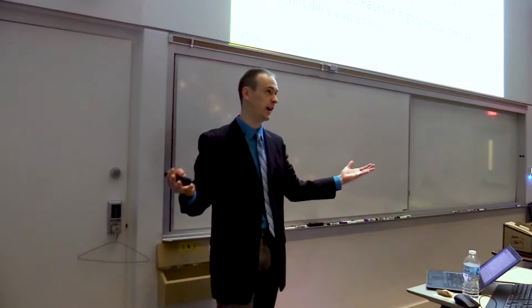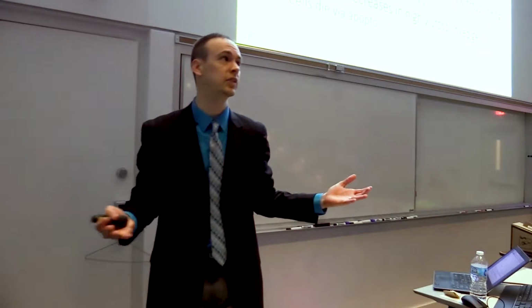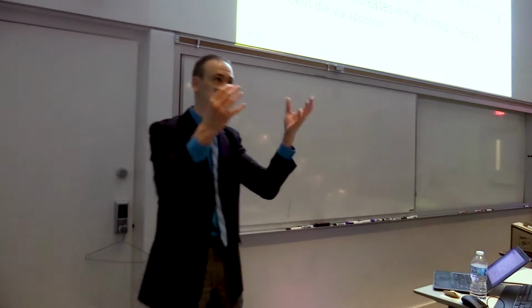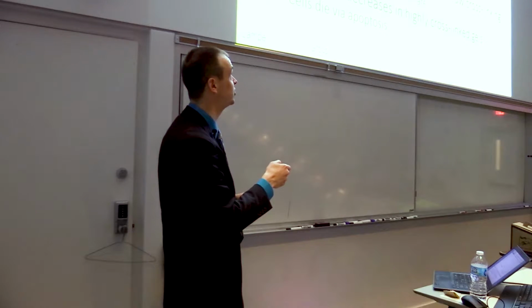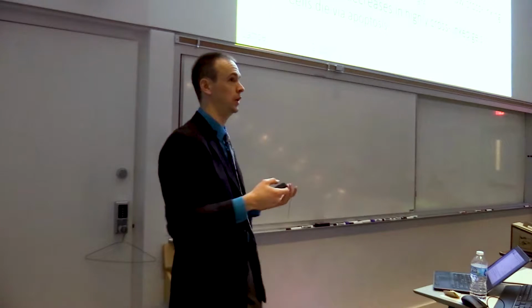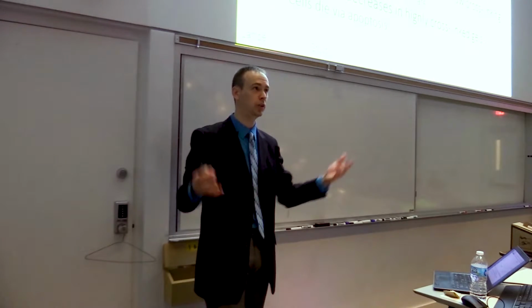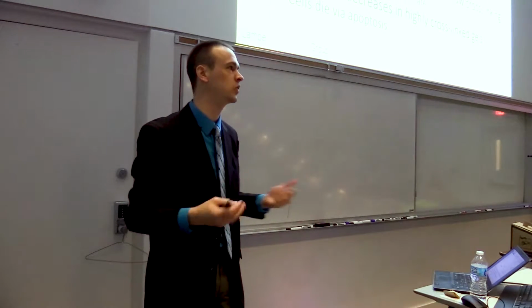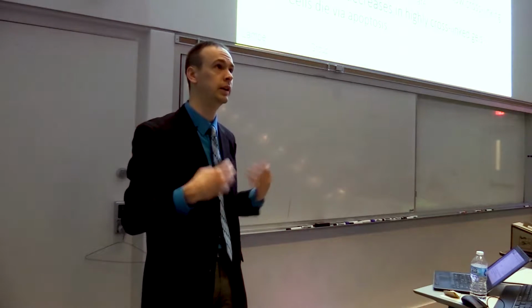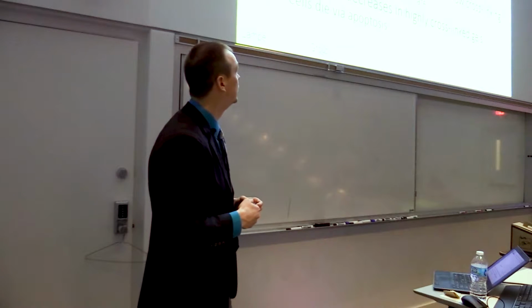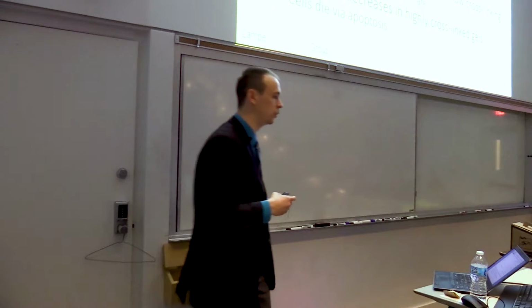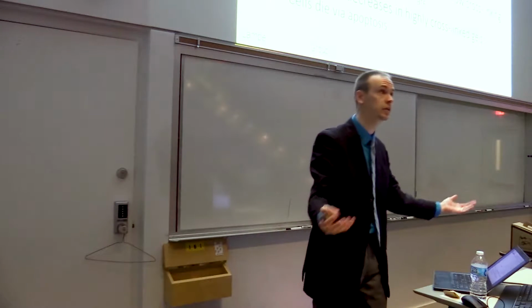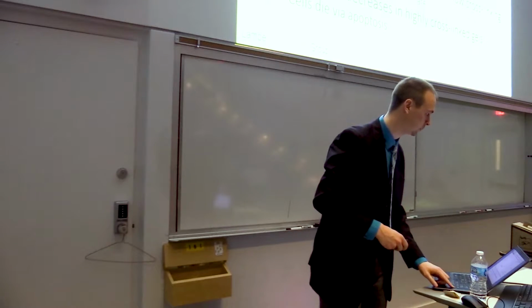So at least one factor that makes a big difference here is the cells that we grabbed from this embryonic brain tissue, when we put them in a material that matches the stiffness that they were taken from, they continue to develop and proliferate and make more neural stem cells, as we might expect them to do in vivo during embryogenesis, right? So this factor, that particular condition, did really well for proliferation. So stiffness matters in the context of neural stem cells, at least.